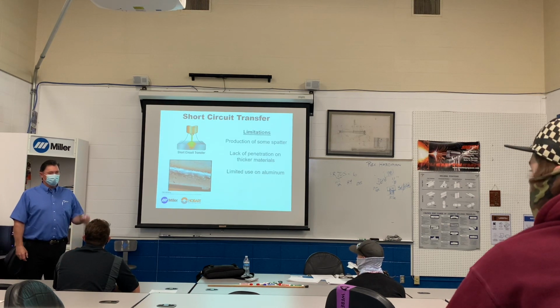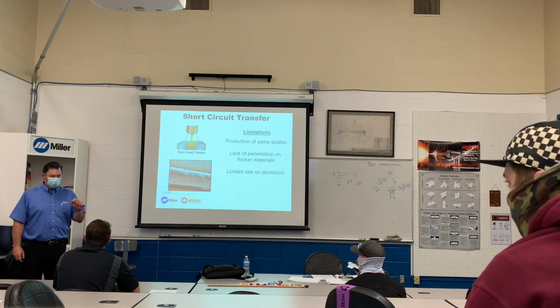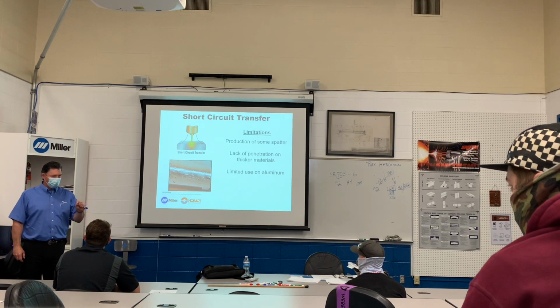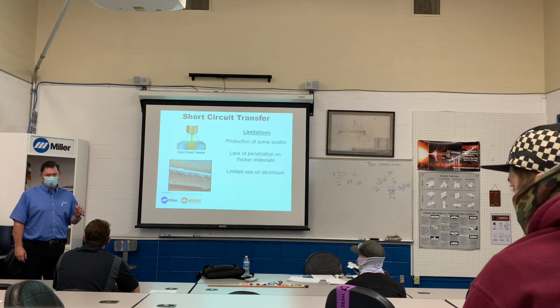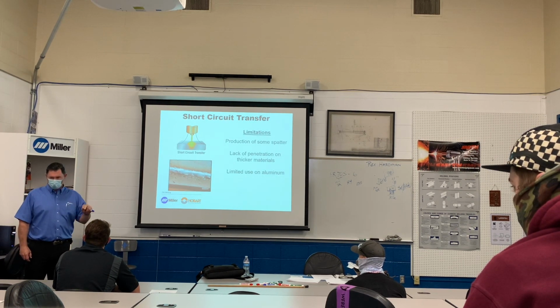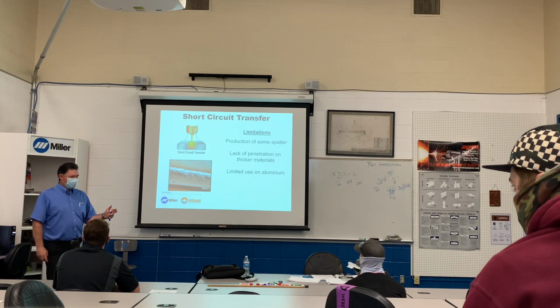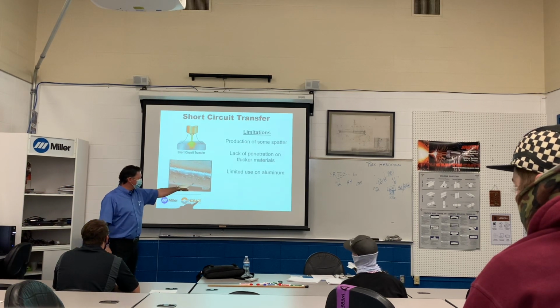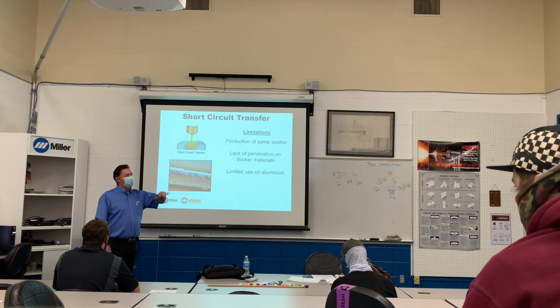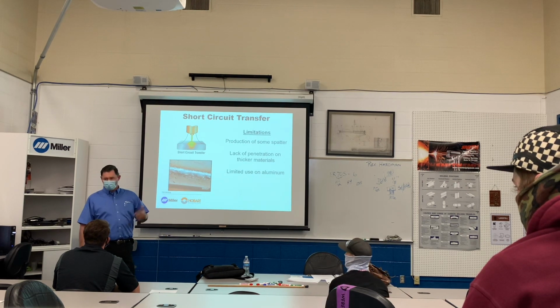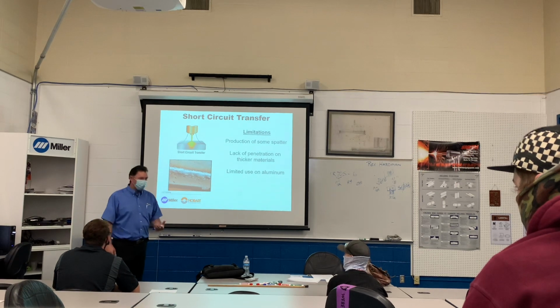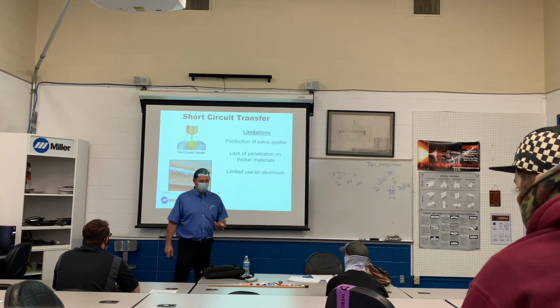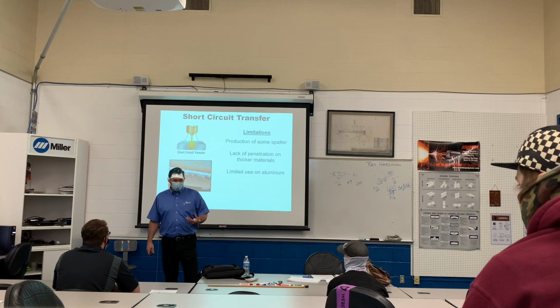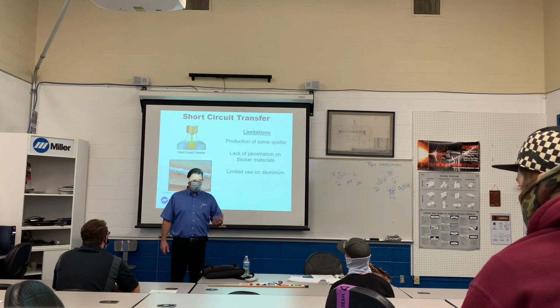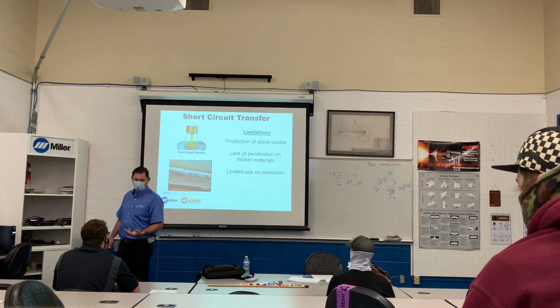Believe it or not, you can get into a spray transfer with small diameter wire on aluminum and do 1/8" aluminum. You can even do 1/16 aluminum in a spray transfer. It does not follow the same rules that steel does. Okay? So never, and the reason we don't short circuit on aluminum is because you're already having a hard time keeping the porosity out of aluminum, even in a spray mode. It's very difficult to get a porosity-free aluminum weld. If you use short circuit on aluminum, you are guaranteed that thing's gonna look like Swiss cheese inside. Guaranteed.